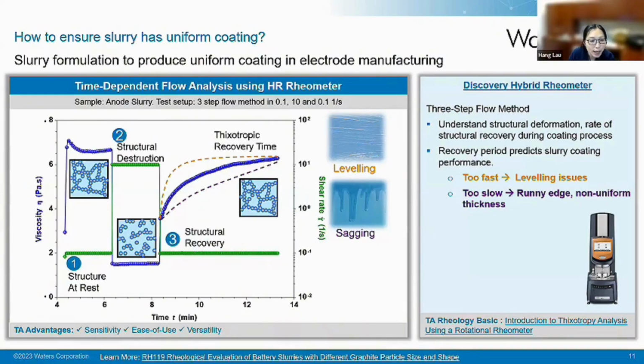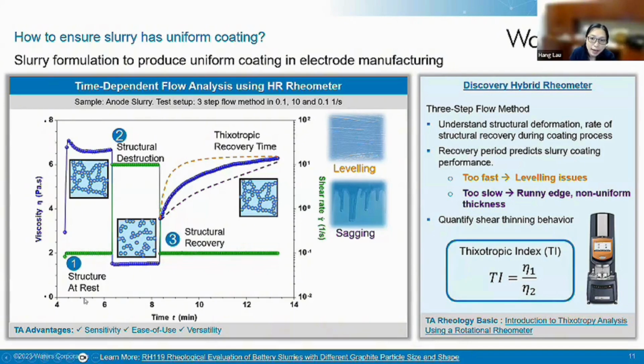Another criterion that you can use to understand slurry much better is what we call the thixotropy index. It is a ratio between your viscosity at high shearing and low shearing regimes. It is a way that you can quantify the shear thinning behavior, and you can monitor or formulate based on how you're adjusting that ratio, helping you understand how good the formulation you will be creating is. Is it fitting for your coating machine?